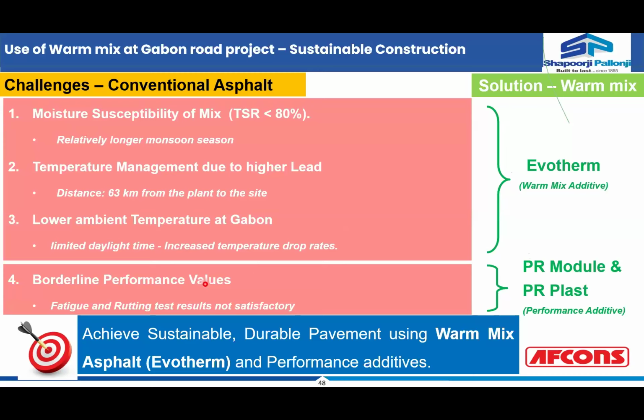Now, whenever the performance values are borderline, when your fatigue or rutting test results are borderline, it's always better to use performance additives also, in combination with the warm mix asphalt. In total this will give you a sustainable, durable pavement and performance by adding the Evotherm and then the performance additives. Performance additives like PR Module and PR Plast are pellets in structure, bituminous and wax-based materials, but generally not used in India. In this particular case we have used them in one of our African projects, which is being shown here.